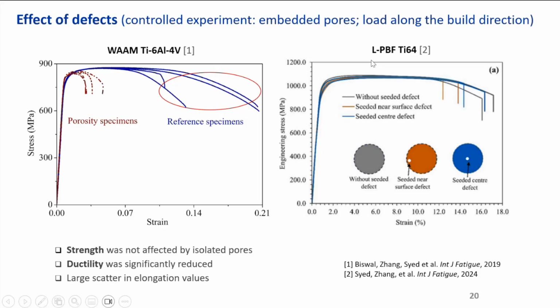And in a separate study of laser powder bed fusion Ti64, it's the same story. Strengths without defects and with defects are similar. They can reach 1,100 megapascal, but the elongation suffers. Without the defects, the black is 16%, but with defects, elongation will be reduced. So what I quite like to say is it's not about how many defects you have. It always depends on the size, and the location probably matters more. So I will conclude this after the fatigue testing section.